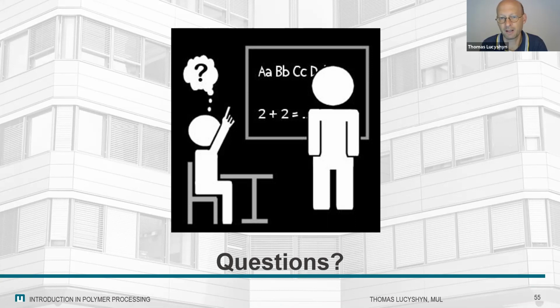In the end, by adding some additives, enhancing the thermal resistance and also the mechanical properties, we ended up producing a product of the same or sufficient quality, made purely of recycled material. This was really a nice result. I will show you this example tomorrow in the recycling lecture.